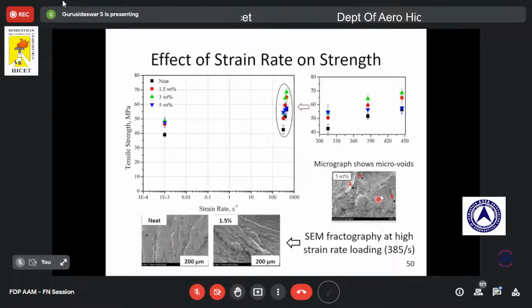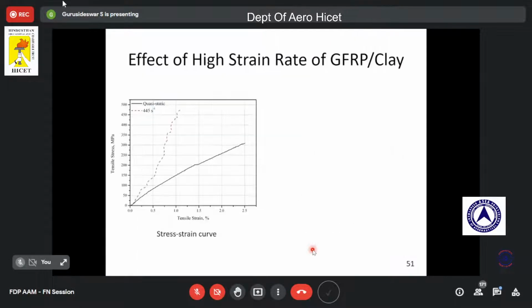Again, this figure shows the confirmation of micro voids at higher clay loading, and this figure shows the micrograph at higher strain rate. You can see the micrograph has a rough surface, so the brittleness of the material has increased. So this is what we observe from this micrograph. Again, this is the effect of strain rate on glass fiber epoxy clay.